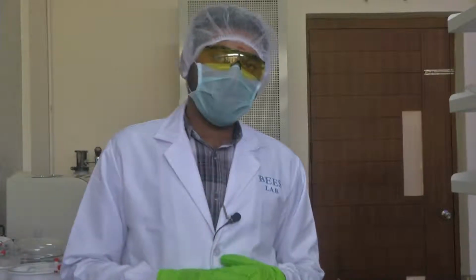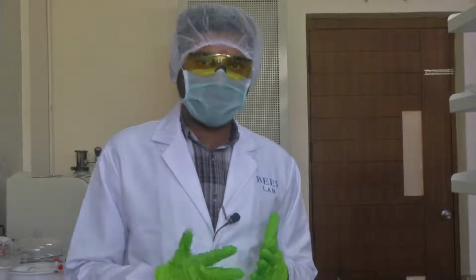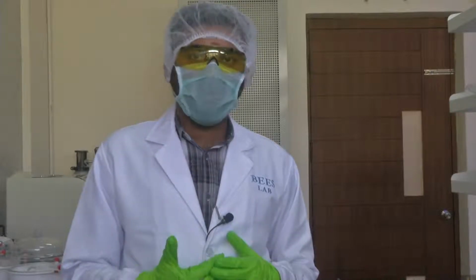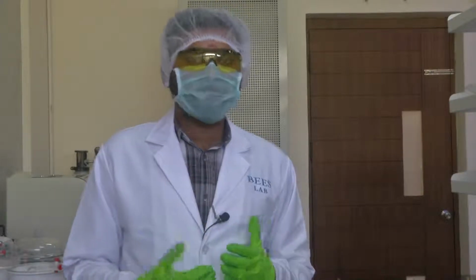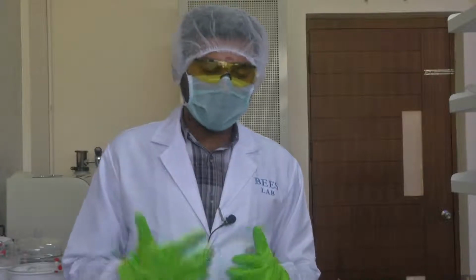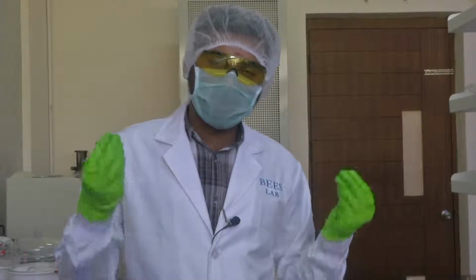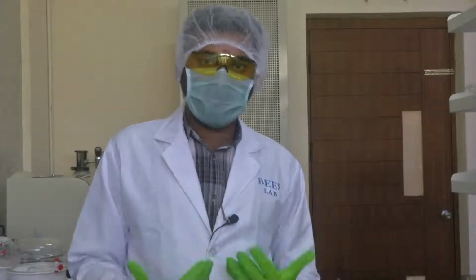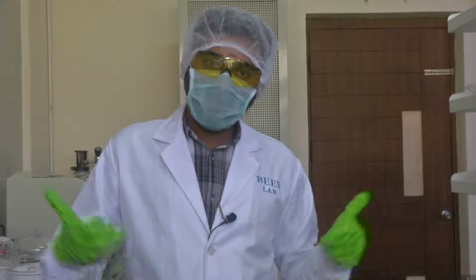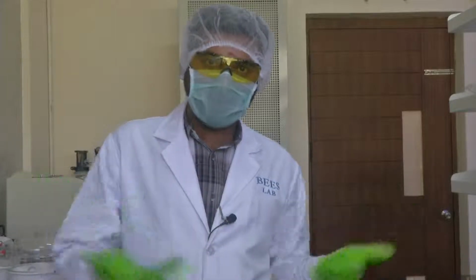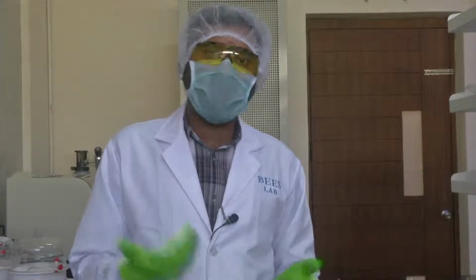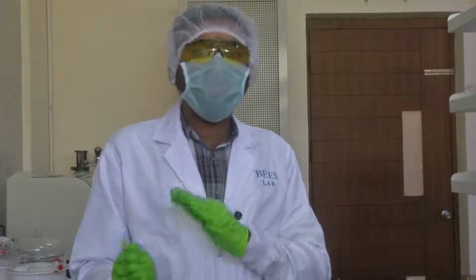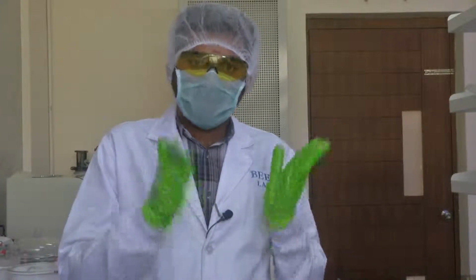So the two critical factors in etching are the etch rate of the etchant, which is directly related to the concentration of the etchant that you use, and the time of etching, how much time you want to do the etching. Why time of etching is important is, one thing is if you keep it in the solution for a long time, even your pattern which you want to preserve underneath your PR will get etched off by seepage underneath the photoresist material. And another thing is, even if you are slightly over time, you will get undercuts in your design.